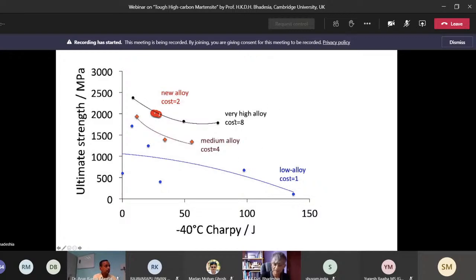And then you have the very high alloy steels, which are like AerMet 100 and so on, with lots and lots of alloying elements. They have a cost of 8. This is our new steel. And on this scale, we have a cost of about 2. And much of this cost comes from the 3-odd weight % of nickel that we have added to this, okay? But if you get a really good service life, then a cost of a factor of 2 compared with ordinary steels is not bad at all, right? So we have high hopes for this.